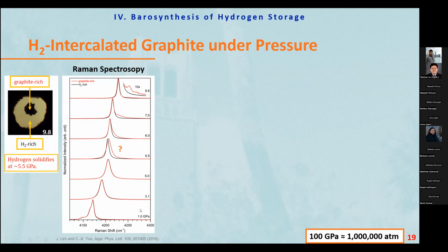This is the typical hydrogen vibron Raman spectrum under pressure. You will see the distinct peak appears at the 4200 wave number. And above 5.5 GPa, you will see an asymmetric peak appears in the graphite rich region. When you apply more pressure, you will see the development of a tail. And when you apply more pressure, at 10 GPa, you will see two small peaks appear in the tail of the hydrogen vibron in the graphite-rich region. So what are they?